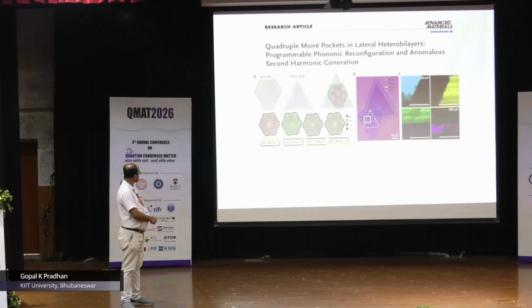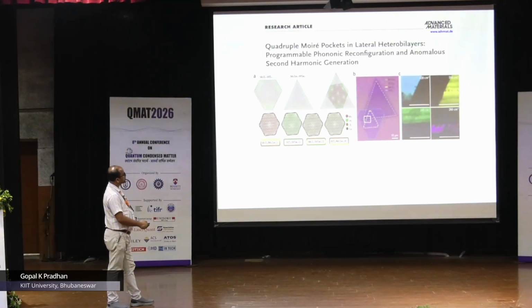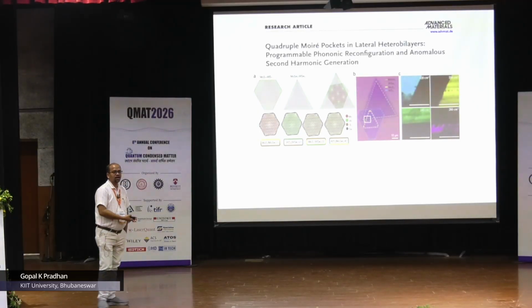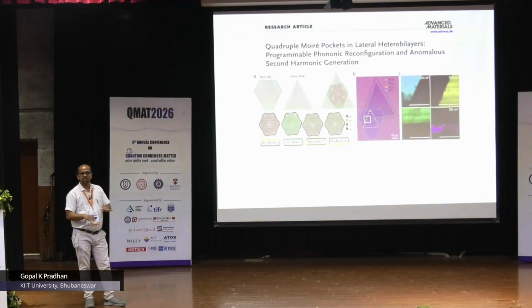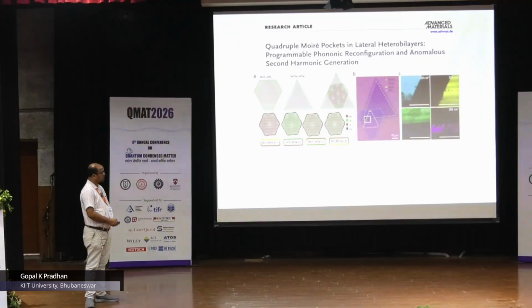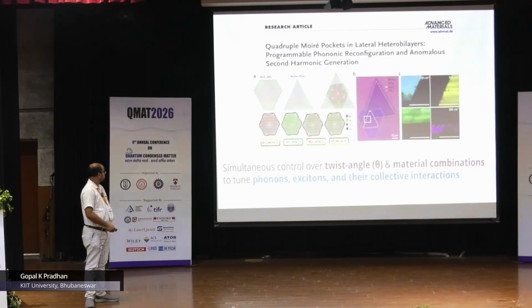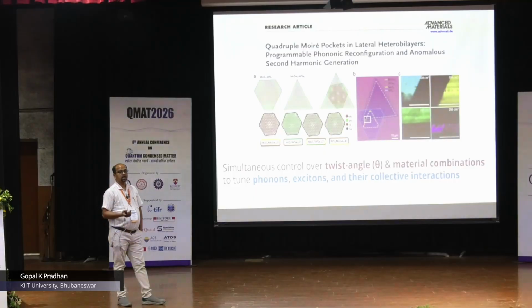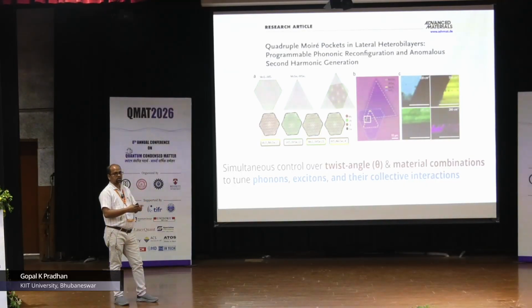So what you see are different systems: MoS2, MoSe2, WS2, WSe2. You can see there are regions here, I think marked 1, 2, 3, 4, I don't know if you can see, and these are the different peaks. It is quite, I would say insane, in terms of the way it has been stacked in all directions, vertical as well as horizontal. And the question one can address here is: can you simultaneously control the twist angle as well as the combination of different materials, in this case different transition metal dichalcogenides, to do what? To tune phonons, to tune excitons and their collective interactions, that means phonon-exciton, electron-phonon coupling, etc.